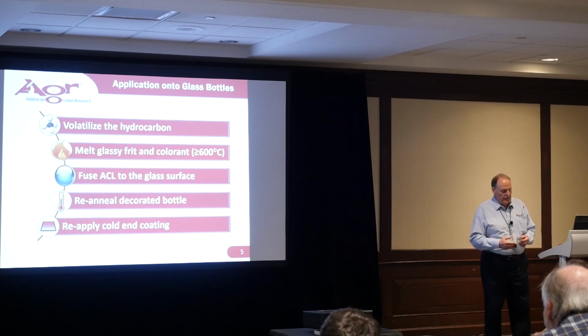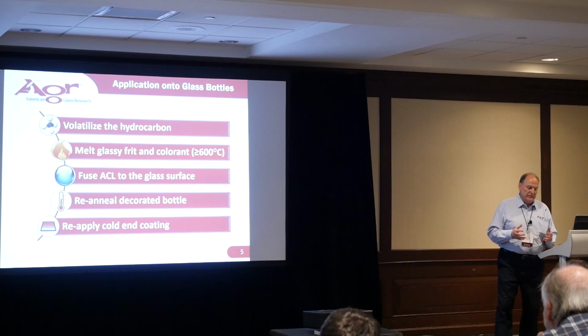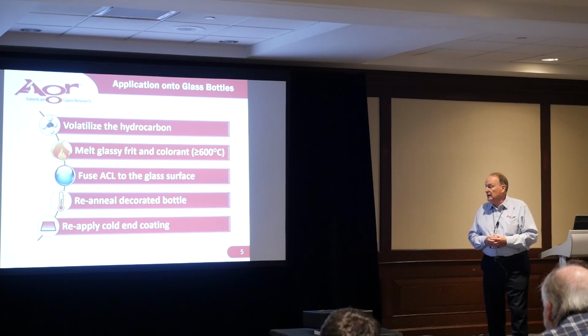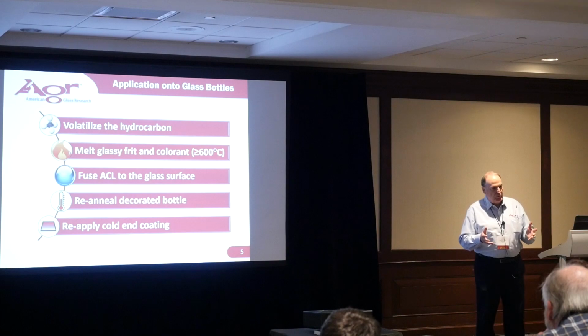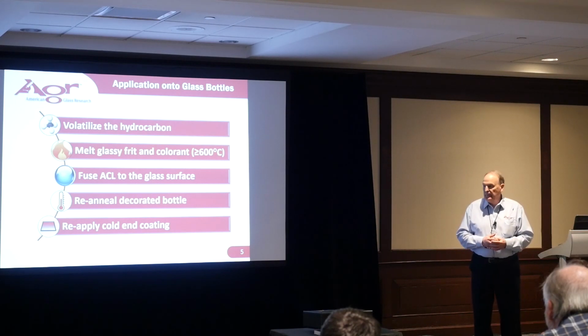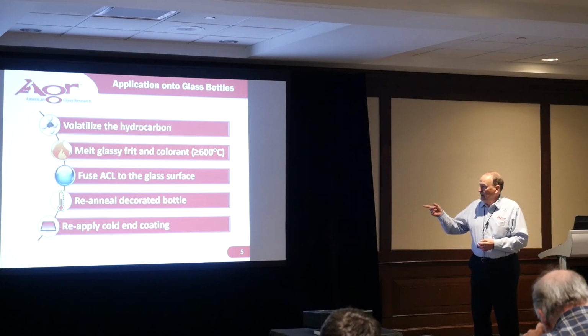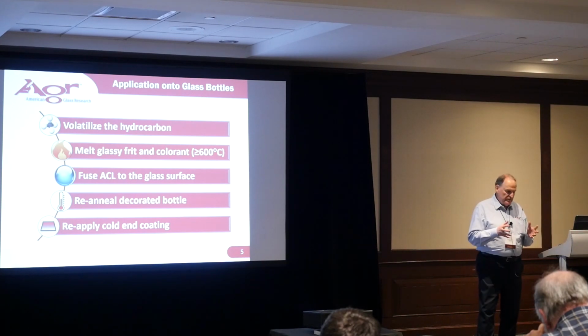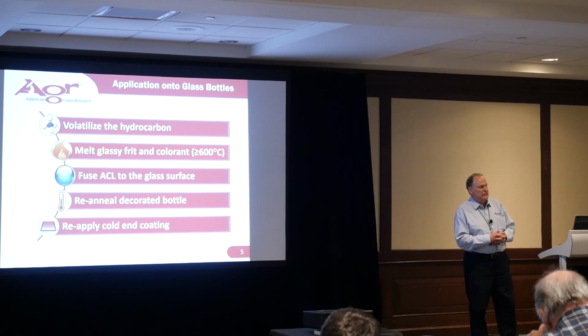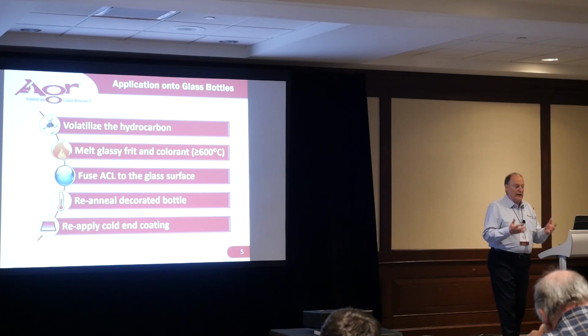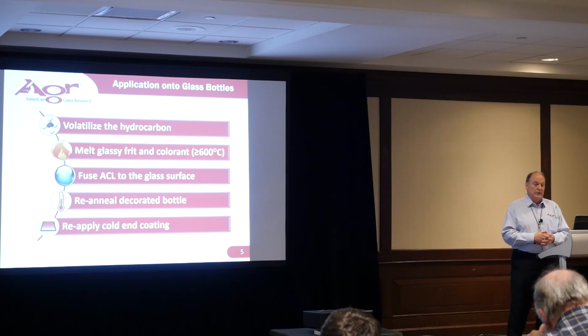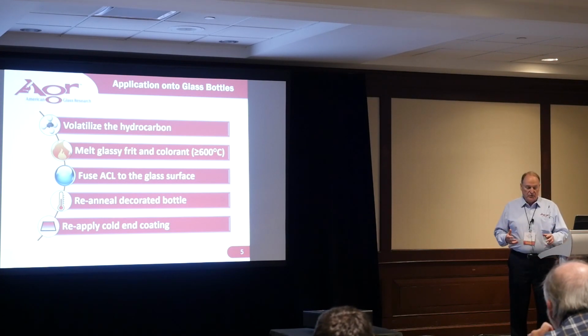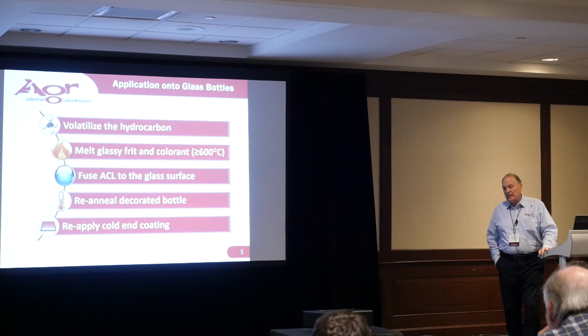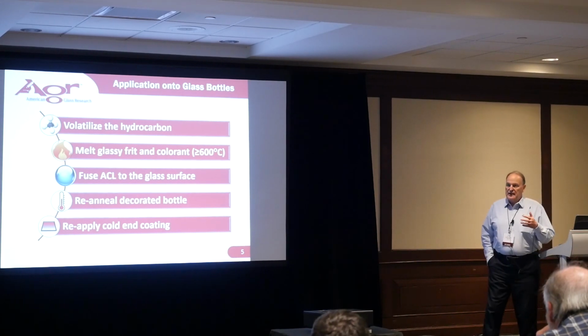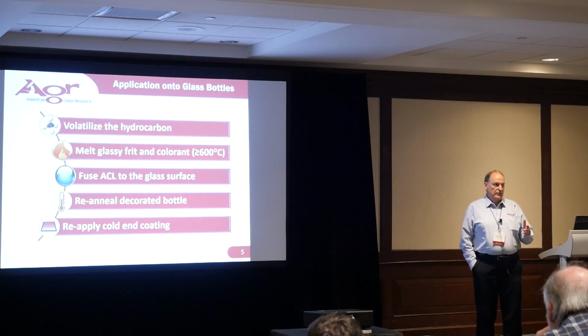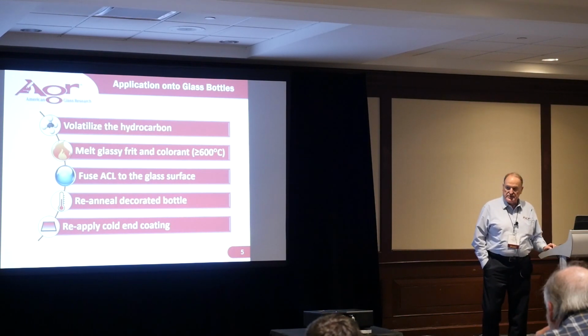Once we get below the strain point of the glass, which is around 510 centigrade, then we can start to more rapidly cool the glass container down to room temperature. Once we achieve about 100 degrees centigrade, maybe 125, then we would reapply what is called the cold end coating. This imparts some lubricity to the glass surface to allow the containers to more easily flow through the filling line in that process.